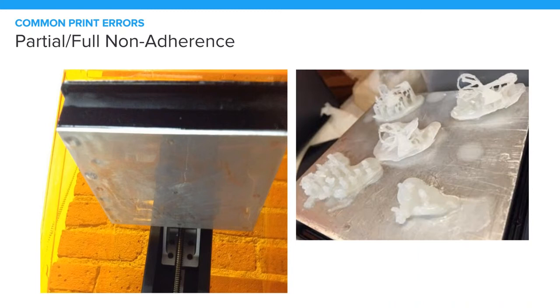Make sure your material settings are set to the proper resin. You can try increasing your base height, like I mentioned before. That'll provide a stronger adherence. And then lastly, if that problem started when you tried a different tank, try fine-tuning the z-axis of your printer. You can adjust this downwards in 1/4 or 1/2 millimeter increments, but you should definitely only try that after you've tried all the other steps.